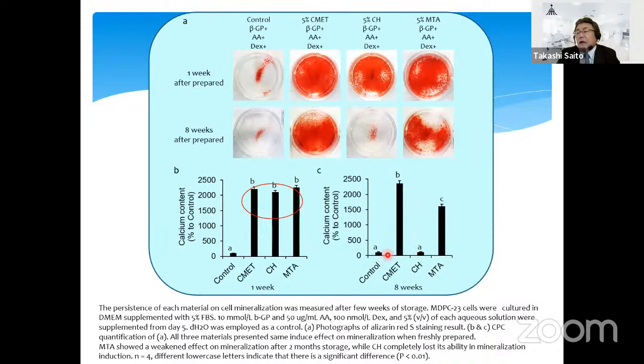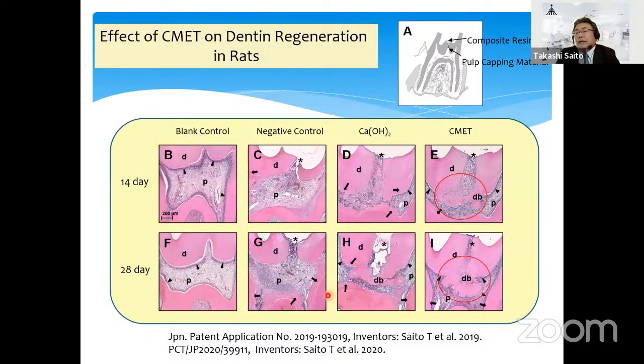I don't show the data here, but according to the results of selective blockage analysis in signal transduction, we found that the MAP kinase P38 pathway is partially involved in the induction of odontoblast differentiation by CMET. Also, we confirmed in a direct pulp capping experiment that CMET induced dentin regeneration on 14 days and 28 days in vivo. CMET induced reparative dentin formation intensively at the early stage of wound healing with less inflammatory reaction of the pulp tissue. So CMET has a dentin remineralization activity as well as dentin regeneration activity.